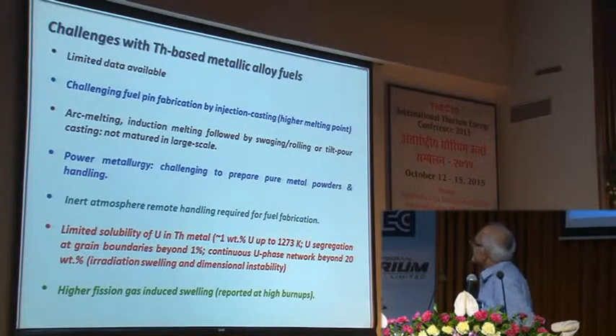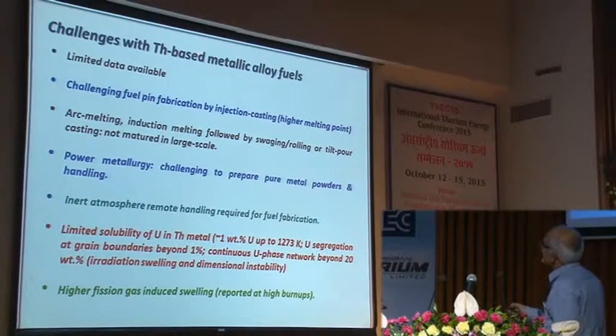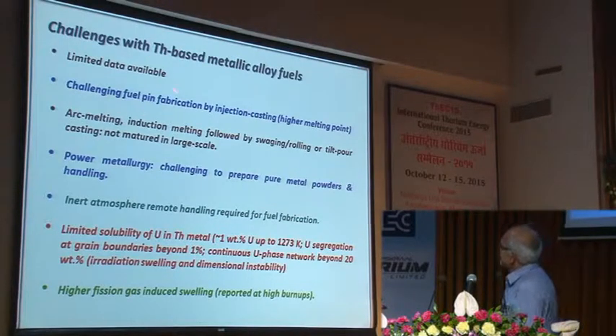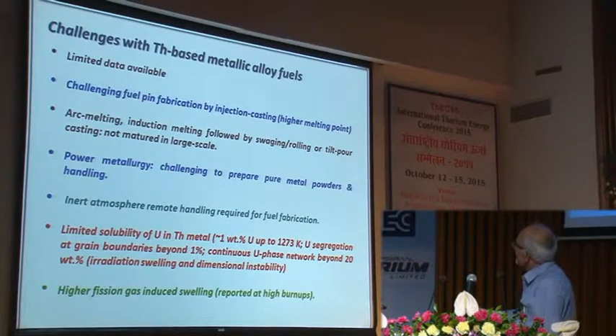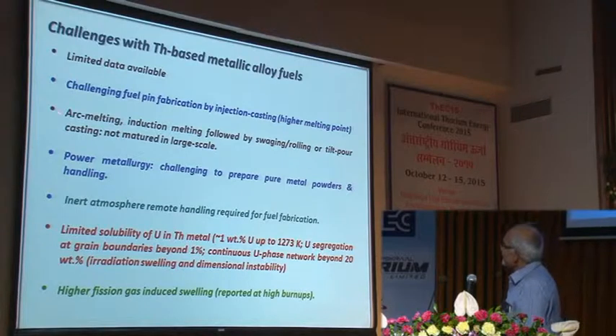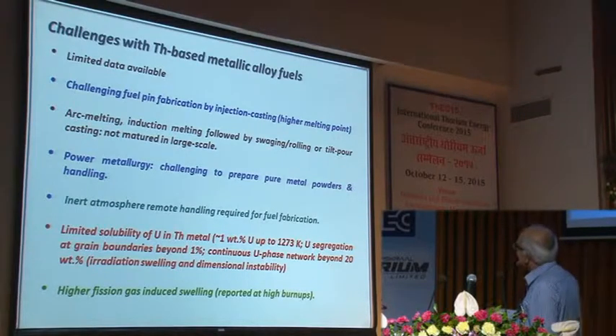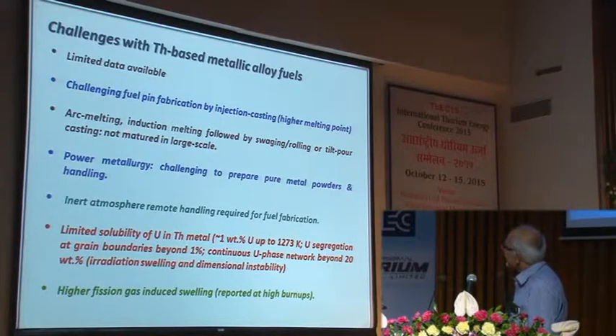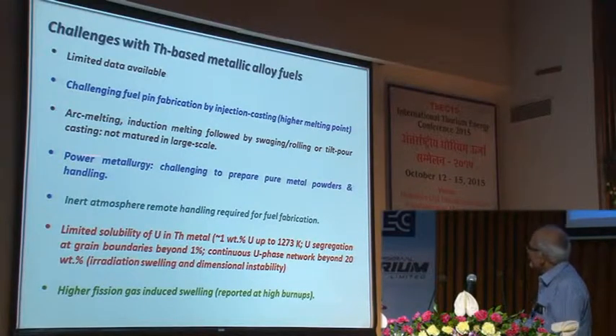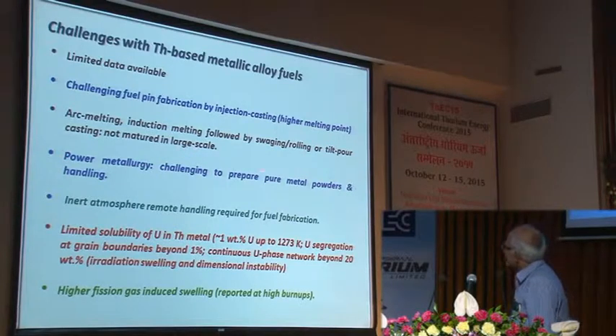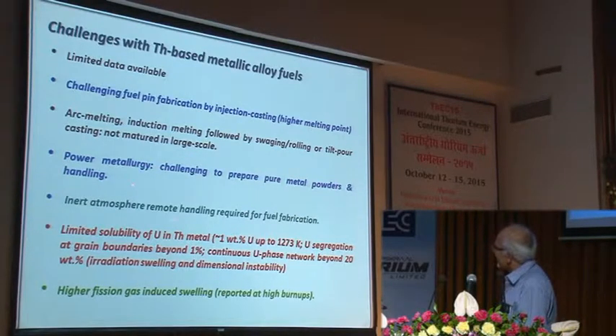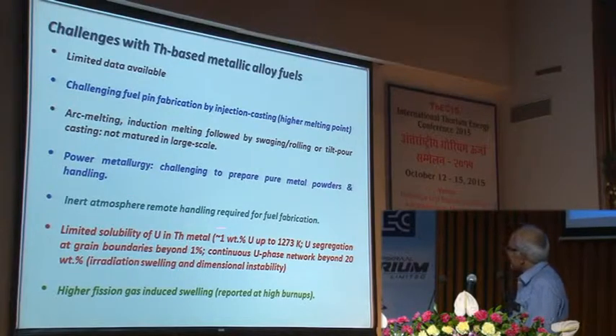But there are challenges with respect to the thorium-based metallic fuels. The data is limited. The challenging fuel pin fabrication by injection casting requires higher melting points. One can, in principle, talk in terms of arc melting and induction melting followed by swaging, rolling, but they are still not matured at a large scale. Still possible to do at a laboratory level. In the morning, Dr. Day talked about powder metallurgy. There are challenges to prepare pure metal powders and handling. You require the inert atmosphere.